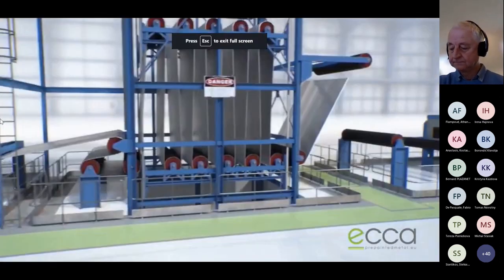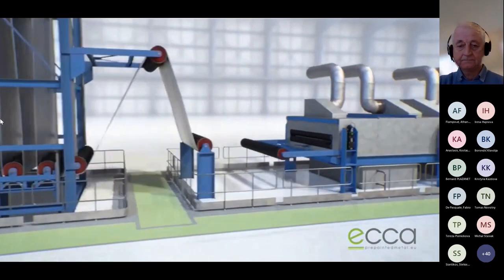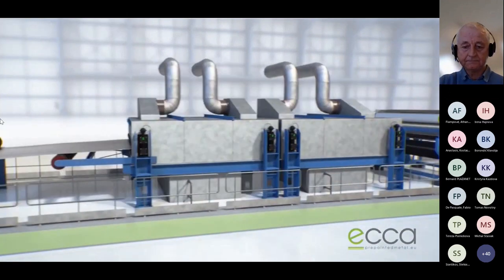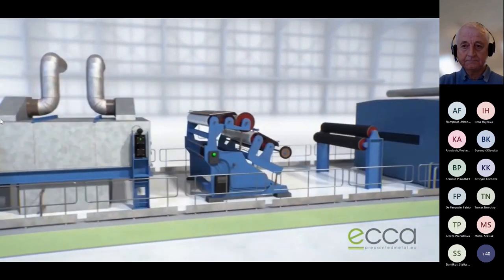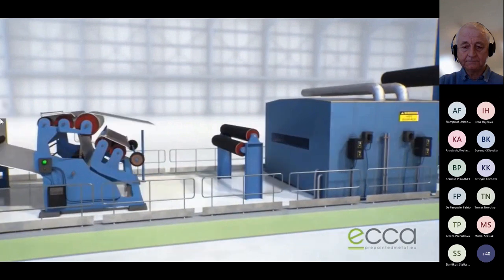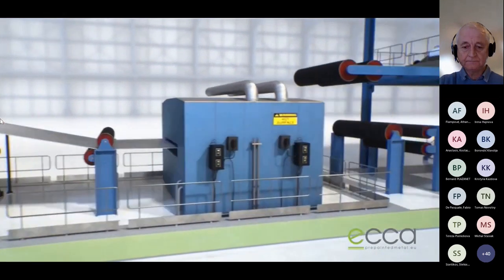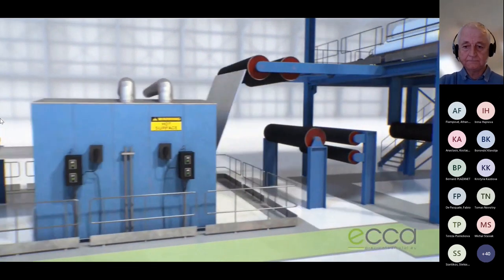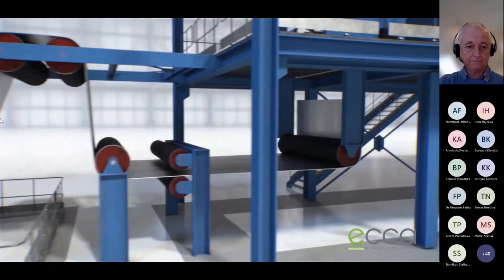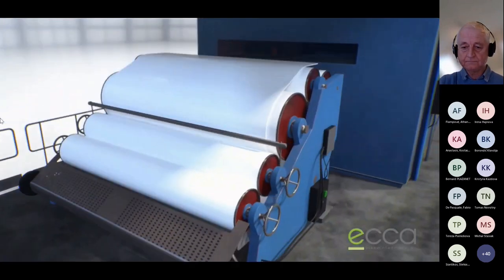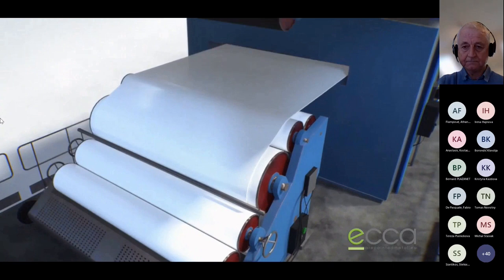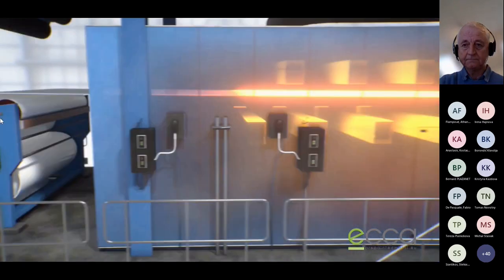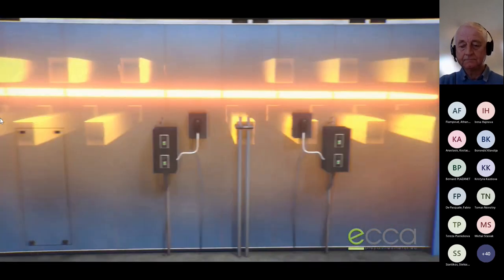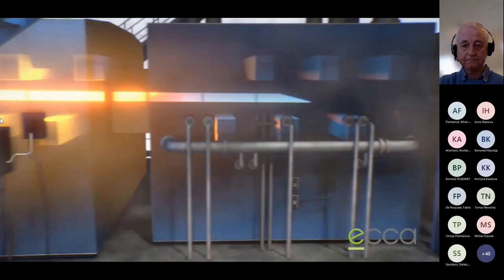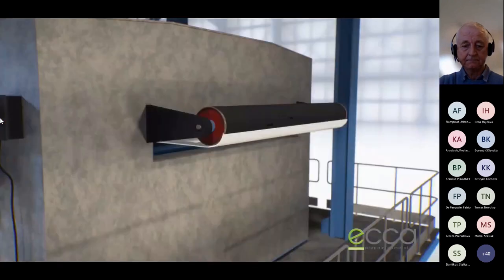The chemical process zones immediately after the entry accumulator in this line consist of cleaning followed by rinsing, the application of a conversion coating followed by a drying stage. The strip then enters the organic coating zone and travels below the first roller coater before it is painted on both sides in the primer coater. It is then cured in an oven, cooled by a water quench and dried with an air blower.